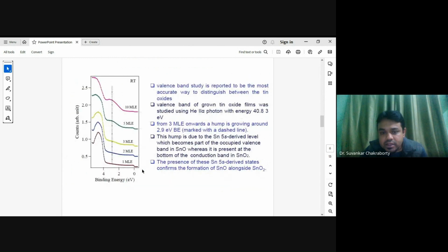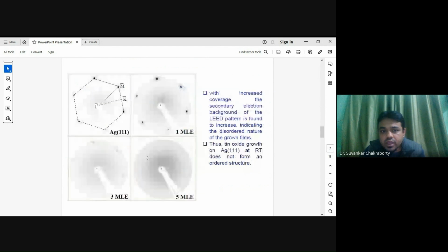Now, whether we have grown SnO or not, the most understandable study is the valence band study, because XPS is not conclusive. So we go to a valence band study and we can see at around 2.9 eV, beyond 3 monolayer actually, there is a hump growing, and this hump is due to the Sn 5s derived level, which we can see only in SnO, not in SnO2. So this proves that there is a presence of SnO alongside SnO2.